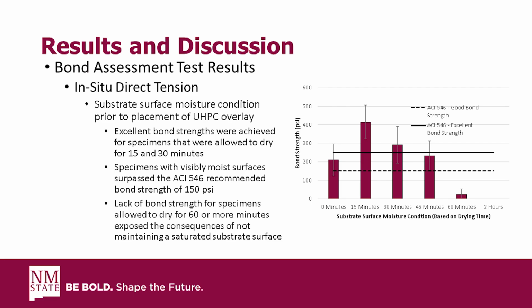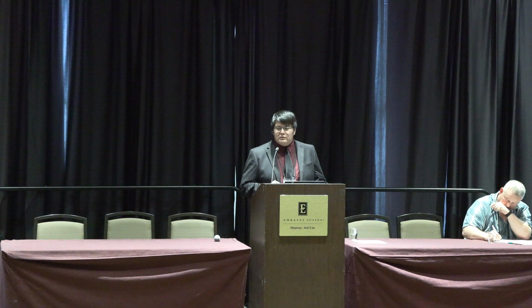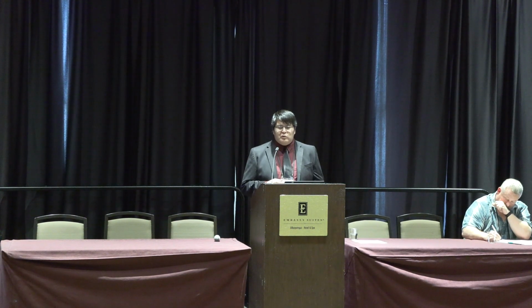And you can see that when we allowed the specimens to dry for more than 45 minutes, for 60 minutes or 2 hours, we did not develop any bond strength. And one thing to note from this is that the 2-hour dried specimen is going to be an exposed aggregate texture, or the heavy sandblasted texture. So this is the ideal case, having an exposed aggregate, an exposed pore space for that to develop bond.